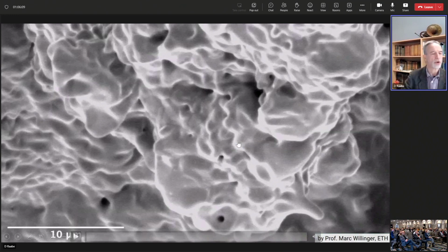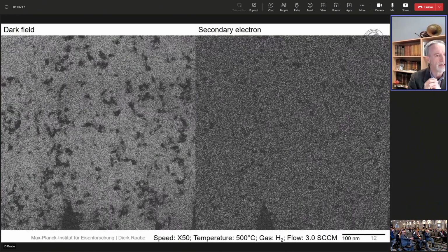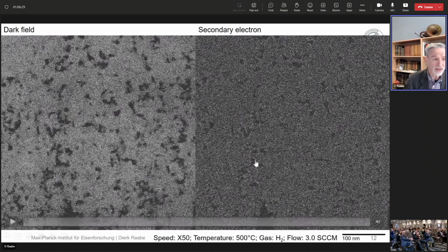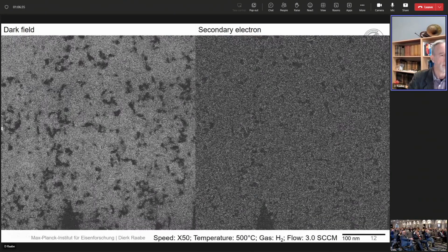Now I go to a second ongoing experiment that is currently done at 500 degrees centigrade. That means we directly start here from magnetite, from the magnetite single crystal, and you are then at a temperature in the phase diagram below the wüstite phase. That means you directly transform magnetite into iron. And that is done now in a transmission microscope, in a Hitachi instrument, again under hydrogen. And let me run this movie. I hope you can see it okay.